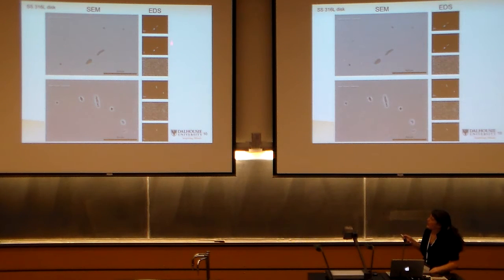And we see that there are manganese sulfide inclusions on our surface. Manganese sulfide inclusions are known to initiate pitting sites, and so with the water treatment, some of the sulfide has been removed from the surface. So these initiating pitting sites are no longer there to create pitting at the low potentials that we apply.